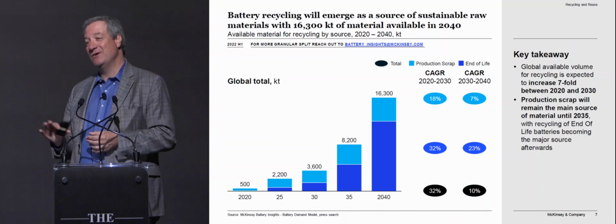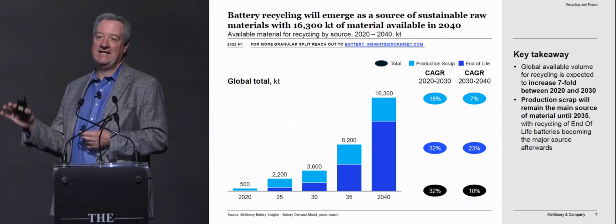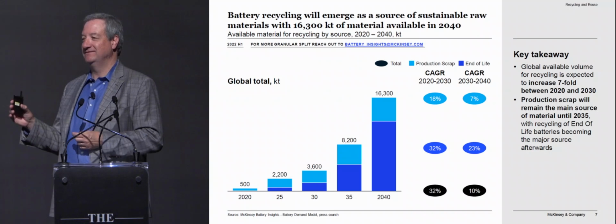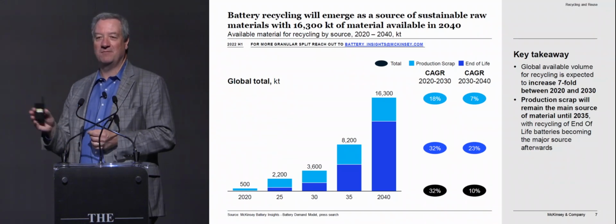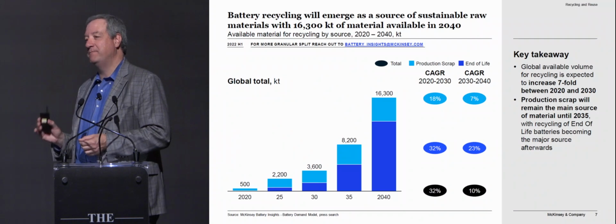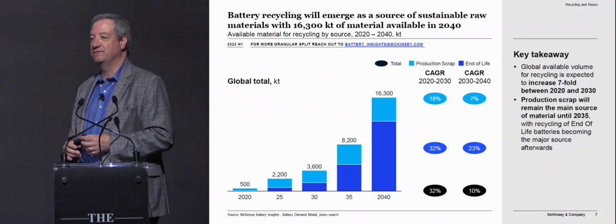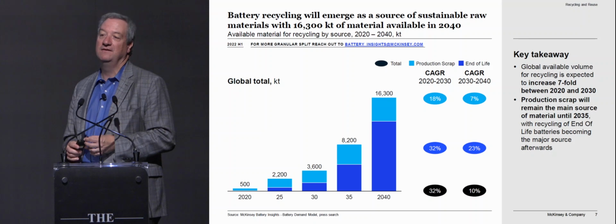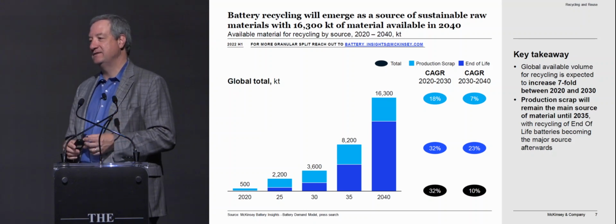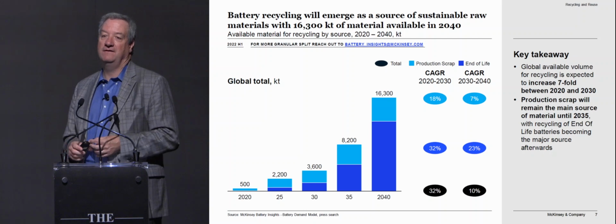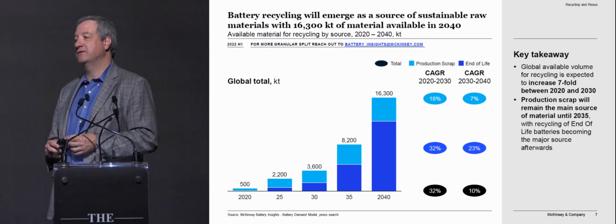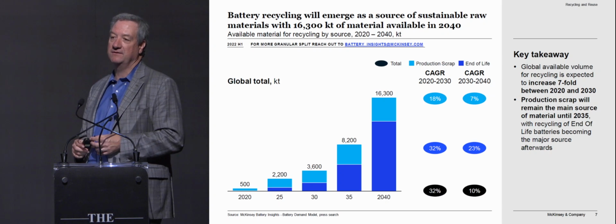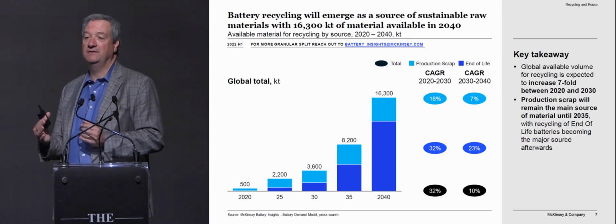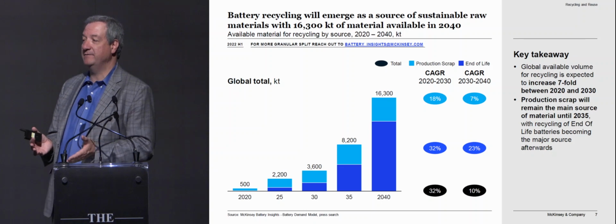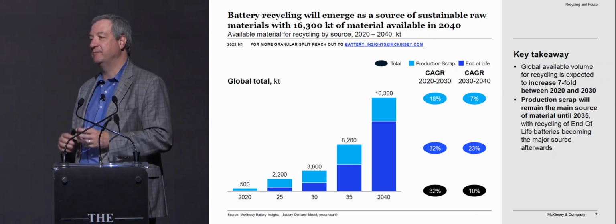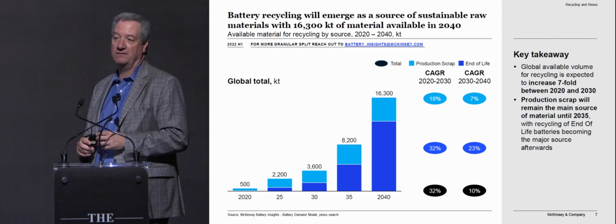But still, at the end of the day, know this: an EV battery today cannot be recycled. No matter what you see on TV, no matter all the companies you read about commercially, the best we can do is throw it in a traditional furnace, melt it down, and get out the nickel, the cobalt, and the manganese. Today, the lithium is not recycled. The graphite anode is not recycled. The electrolyte is not recycled. The separator is not recycled. So you can get the copper foil on one side, you can get the aluminum foil, and you can get that cathode material, but the rest of it is just either burnt off or landfilled.